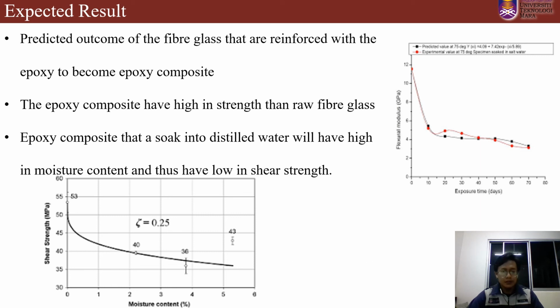The epoxy composite that soaks in distilled water will have high moisture content and thus have low shear strength. This is an example of the graph, which shows that when the specimen soaks in the distilled water for a long time, the shear strength of the specimen will be low.